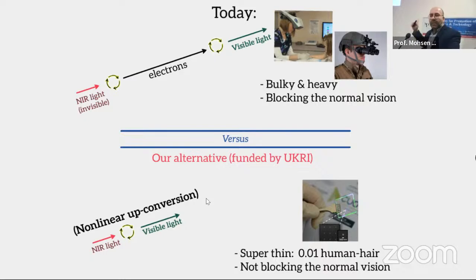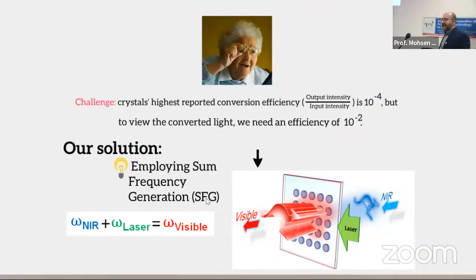So it worked. We proposed this idea, and we got very good funding to do the research, and we continue doing that. At some point we realized that just investing in efficiency is perhaps not the best strategy, because we can only increase the efficiency to some extent when these nanoparticles convert near infrared to visible light. So what we did was use frequency mixing. We got one more laser, one more light involved as a facilitator, so that when, for example, we have very low-intensity near-infrared light, it can get mixed with this high-intensity laser and generate high-intensity visible light, and at the end we filter out this laser. So by having one facilitator, you can compensate for the low efficiency of this nanoparticle in changing the